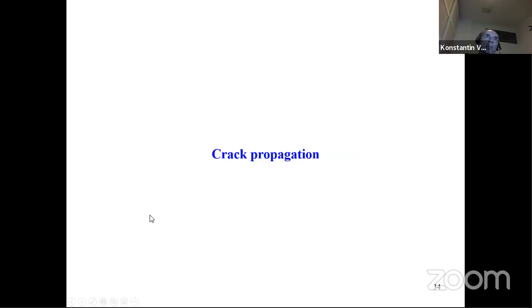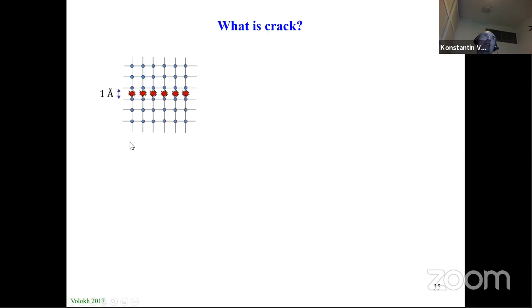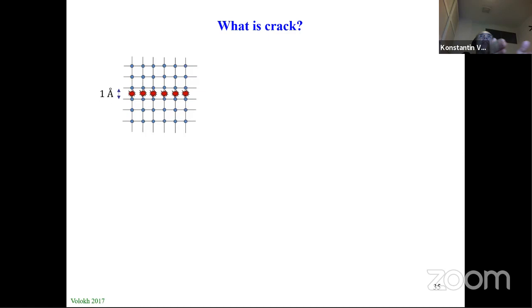Now I go to crack propagation — fracture itself. The key question is: what is a crack? It sounds simple, but the answer is not simple. People usually think about a crack as a separation of two adjacent atomic layers — typically on the distance of one angstrom to one nanometer, a typical interatomic distance. So people think of a peaceful unzipping of two adjacent atomic layers. This assumption is intuitively appealing because it is simple. But wait: the smallest size of an object recognizable by the naked eye is about 60 microns. If a crack were a separation of two adjacent atomic layers, we wouldn't be able to see the closed crack — but we do see cracks.